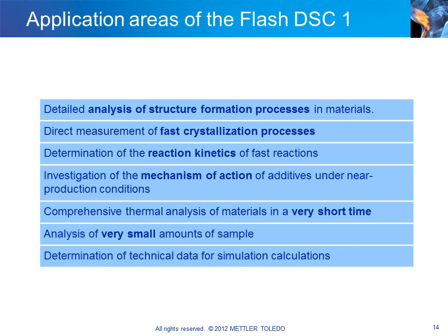Because the scanning rates are so high, comprehensive thermal analyses of materials can be performed in a very short time. For example, the investigation of the cooling rate dependence of a crystallization process in a range of more than 3 decades takes less than 30 minutes. The Flash DSC-1 allows the investigation of very small amounts of sample down to just a few nanograms. Data can be measured under actual process conditions. This can be used in simulation calculations, for example, to optimize the performance of tools.